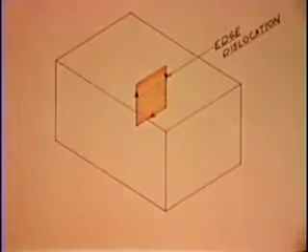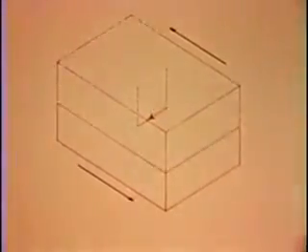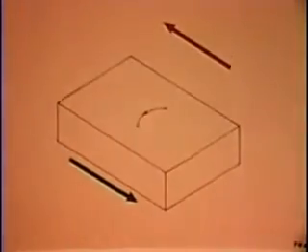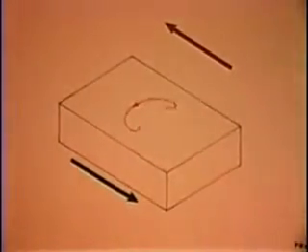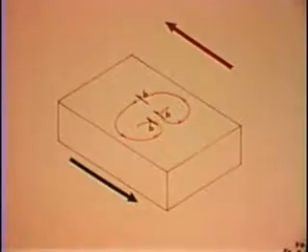Under stress, a dislocation pinned at 2 points in the slip plane bulges between them. The portions close to the pinning points rotate around them and approach each other. As parts of a single dislocation, the approaching segments have the same Burger's vector, but opposite directions.